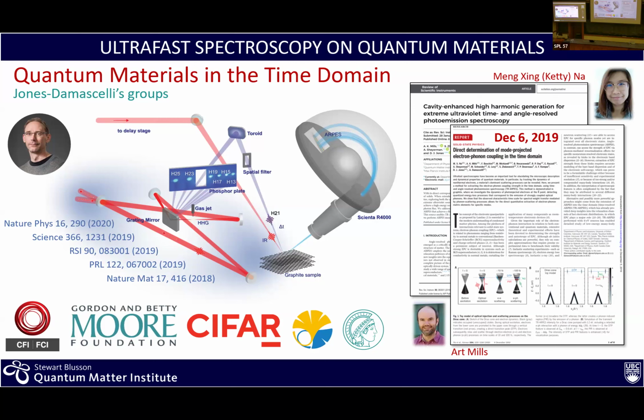And these two quantities are related by Heisenberg. And so then you have to really be able to fine tune both of them to get the best of the two. So basically we're pushing, just in terms of numbers, for something like 200 femtosecond temporal resolution and 15, 20 milli-electron volt energy resolution. So that's really the challenge here.